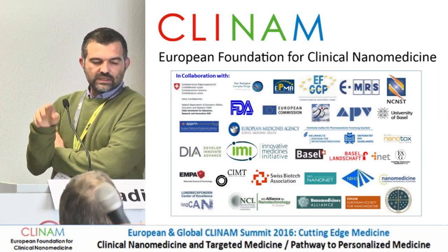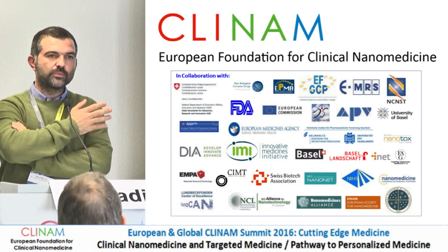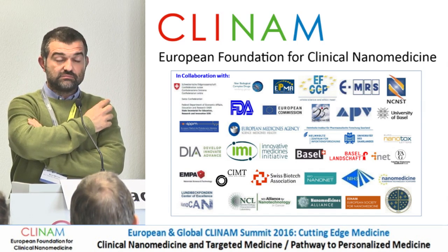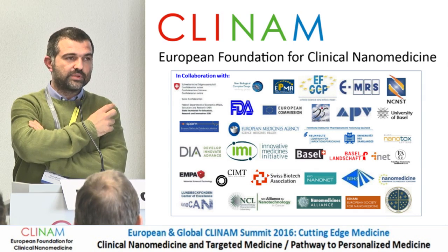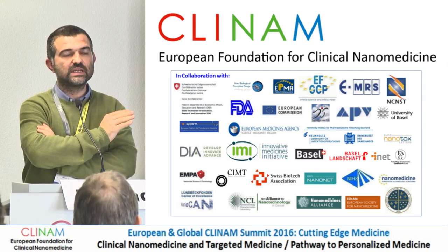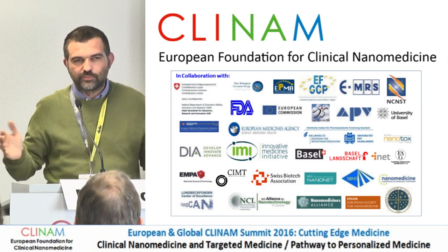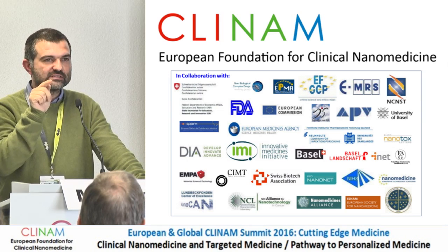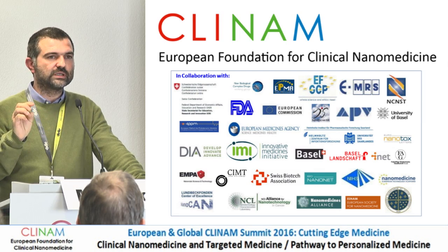That's a good question. I don't have direct experience with protein corona on this nanoparticle, but I work a lot with gold nanoparticles coated with sugars. Sugars are PEG-mimetics, and the advantage of sugars over PEG is that they are completely silenced to the immune system — unlike PEG, against which we can find IgG antibodies. About protein corona, my experience is that unless you want to target a specific lectin, you don't have this kind of attachment.